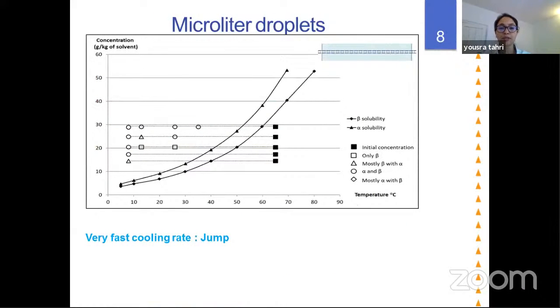So for our experiments in the microfluidics, we always start undersaturated, and we go to the final temperature and we wait to see what will be crystallizing inside of the droplets. Here it is important to note that in each experiment we had many tubings, and we stored more than 50 droplets. So each experiment has more than 50 droplets, so it's many nanocrystallizers.